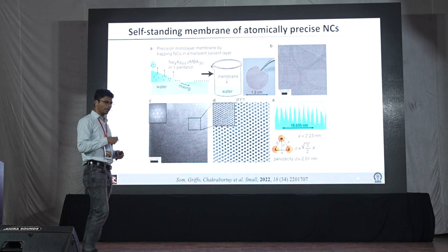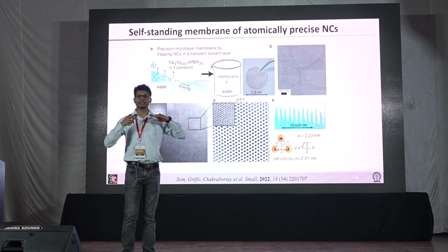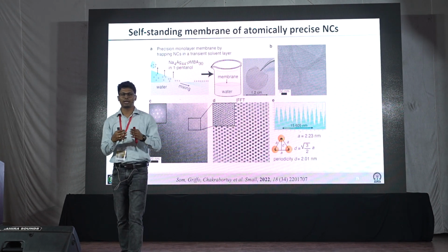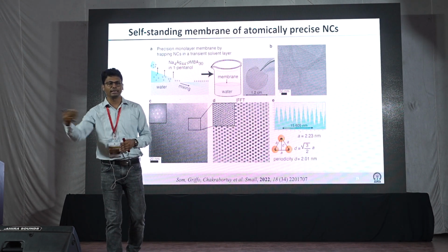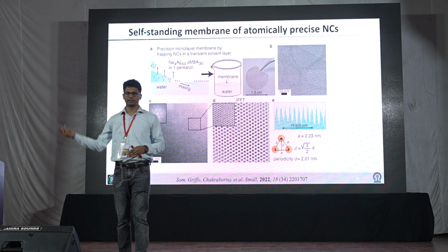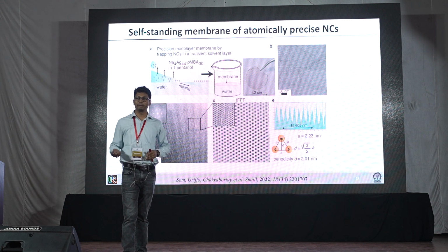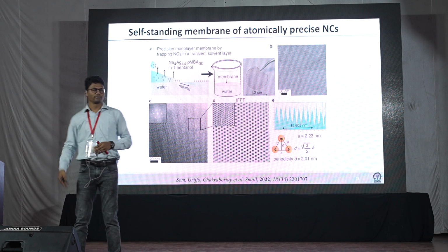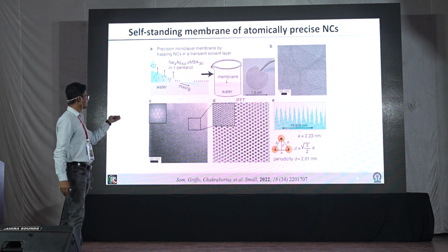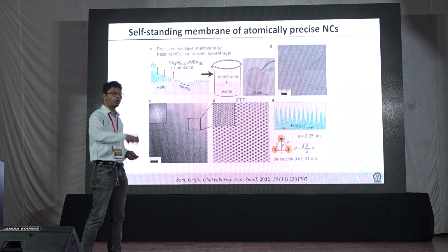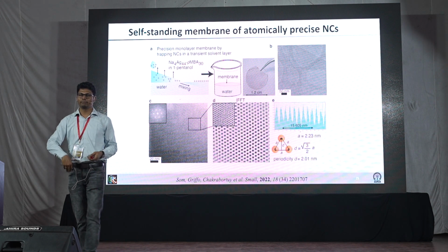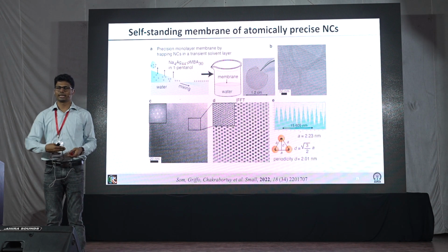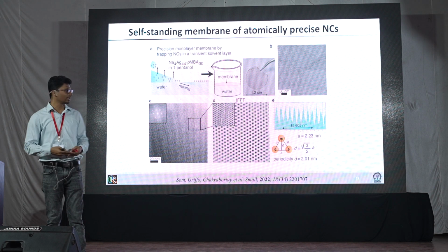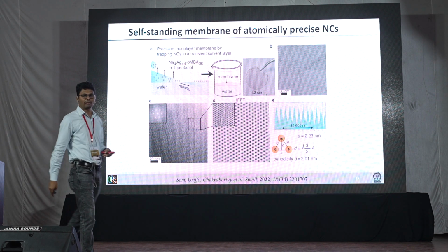With this idea, what comes next is that if clusters can form hydrogen bonds on top of a tellurium nanowire surface, why can't they form directly there, like a freestanding membrane, as we have seen. So freestanding membrane, that was the next goal. And we did carry out these experiments and found that a monolayer of clusters, a self-standing membrane, is possible with the same methods which we tried there. And you see nice hexagonal patterns are there.